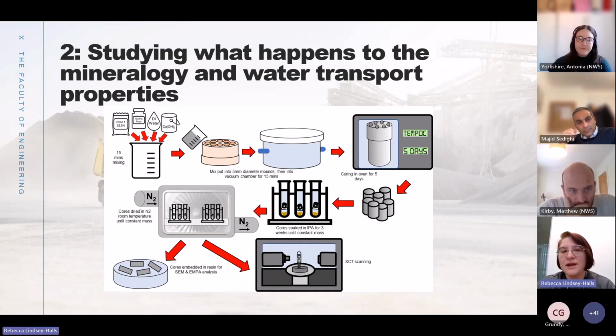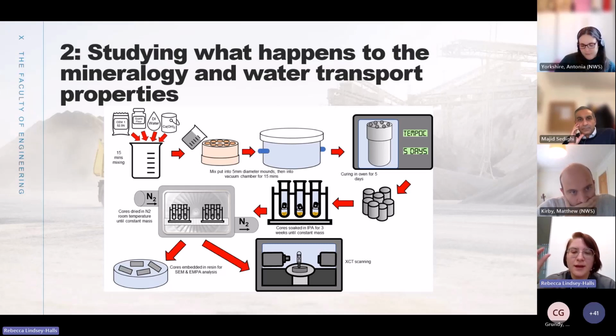So this is the second aim. This is what's happening to the mineralogy and water transport properties. The difference in preparation for this is that the same cores are coming out of the oven, so it's the same mixture, so they should be comparable. But instead of being freeze-dried and ground, which destroys the microstructure, they're soaked in alcohol for 3 weeks. So the alcohol replaces the water inside the pores and still arrests the hydration. Then some of these have been scanned with the XCT machine and others have been embedded in resin.